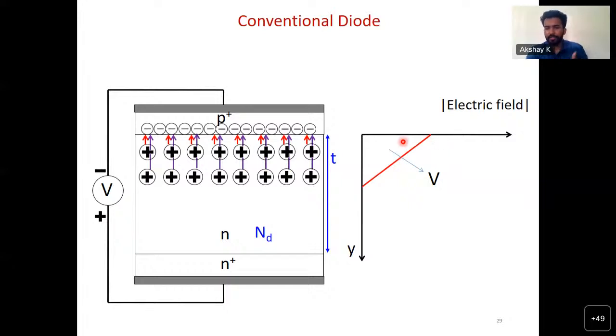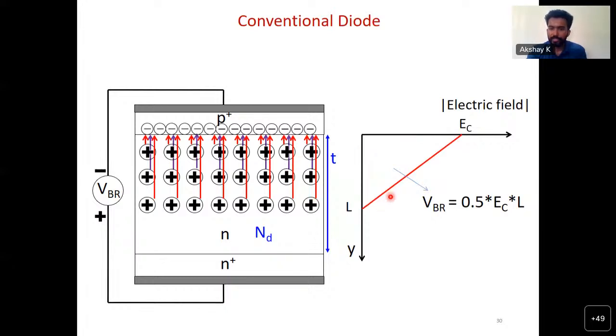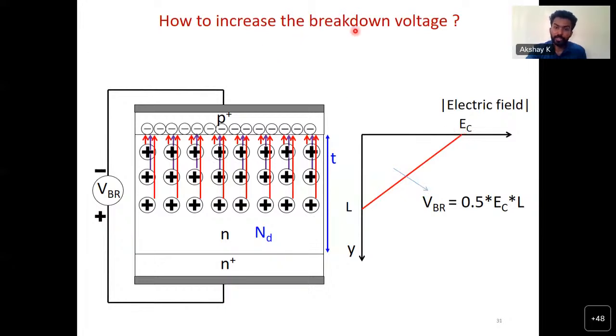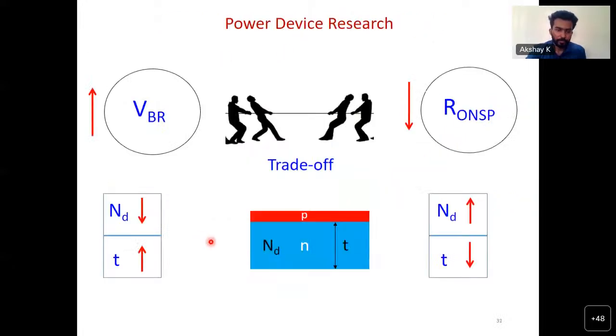Now, when you keep increasing the reverse bias across this diode, there comes a point where the electric field at the junction increases to a value we call the critical electric field, and that is a material dependent quantity. For instance, for silicon, it comes around 300 kilovolt per centimeter. Around that electric field magnitude, the device electrically breaks down, and you can't apply any further voltage across it in reverse bias. So that's what it means. Now the question is, how do you increase the breakdown voltage in this scenario? One way of increasing it, or the two ways that we have, is to reduce the doping and increase the thickness. Why?